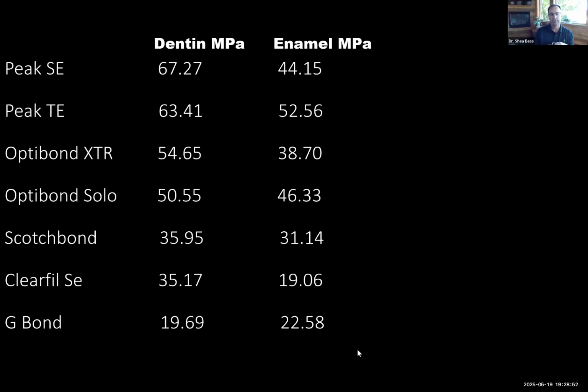So here's a quick recap of the ones that I've talked about. I'm not going to give you all of my numbers tonight, but if you look at this chart here, look at the difference between the dentin bond strength of, say, a Scotchbond, which is a great product, by the way. But if you compare that bonding to dentin to, say, Peak SE, using Peak Universal Bond, using their self-etch, you're going to get nearly twice the bond strength than you would with, say, a Scotchbond, and 3 times more bond strength to dentin than you would with G-Bond. And also with enamel, look at Clearfil SE coming in at under 20, and compare that to, say, OptiBond Solo at 46, or Peak Universal Bond under a total etch, which is 52. Again, you're going to get 2.5, closing in on 3 times the bond strength.